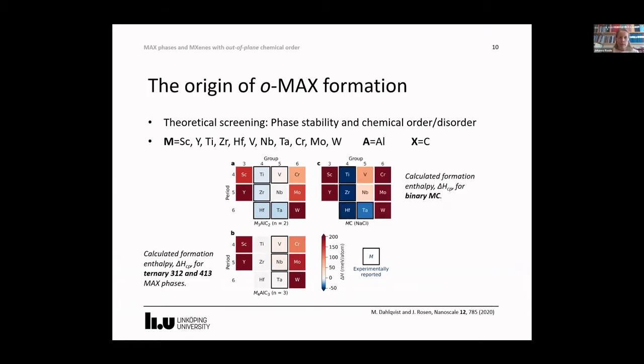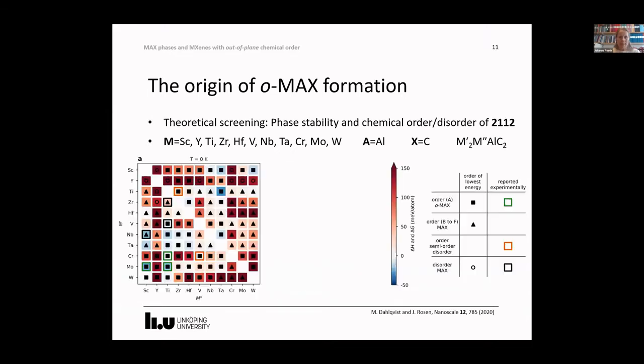The trends in stability for both the 312 and 413 are similar to the trends found for the binary metal carbide in its rock salt structure, where M elements from group 4 and 5 are giving stable or close to stable carbides, whereas elements from group 3 to 6 give phases that are far from stable. And the comparable trends between these two can be related to the stacking of the metal and carbon in the metal carbide layers of the MAX phases, which is also found along the 111 direction of rock salt metal carbide. But now we go from the ternaries to quaternaries and possible o-MAX formation for 312 phases, or what we can also call 2112 phases with a formula like this.